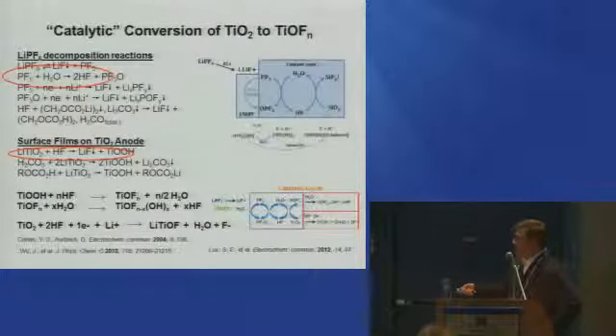If this was a lithiated state, there are other degradation mechanisms that I won't get to, but in the delithiated state, if you've created any surface hydroxyls, you can get direct reaction of the HF to make more water. That is a catalytic cycle, because if you put water in, PF6 decomposes to make more HF, so you've got a lot of recycling in this. In addition, most people think about lithium insertion in titanium, or proton insertion, and they typically talk about cation insertion.